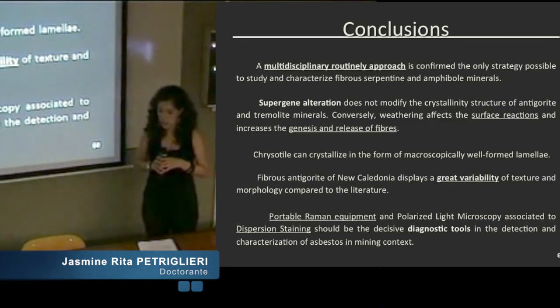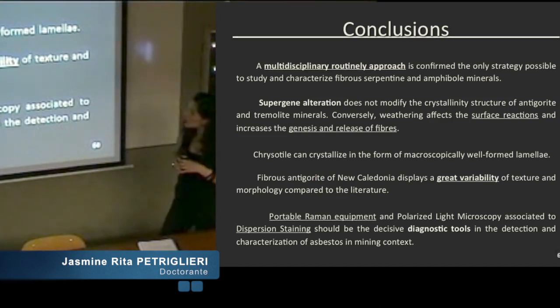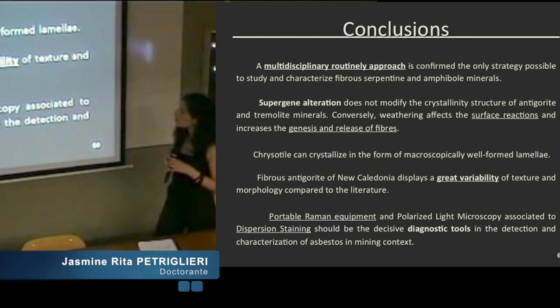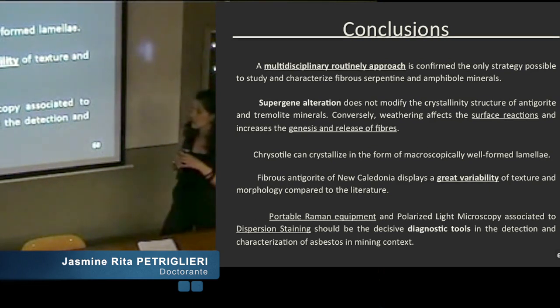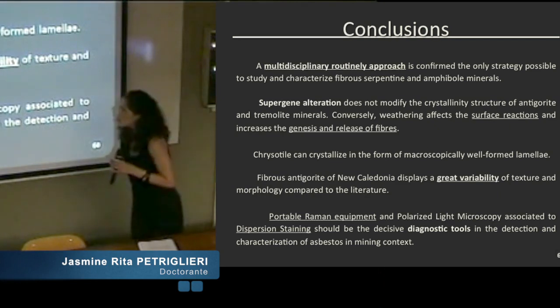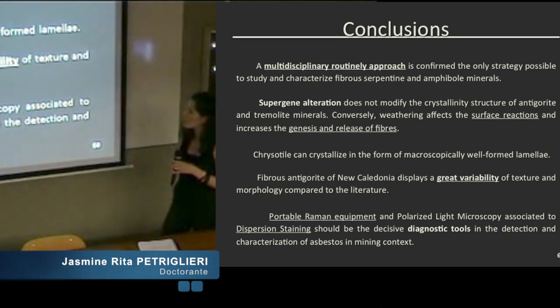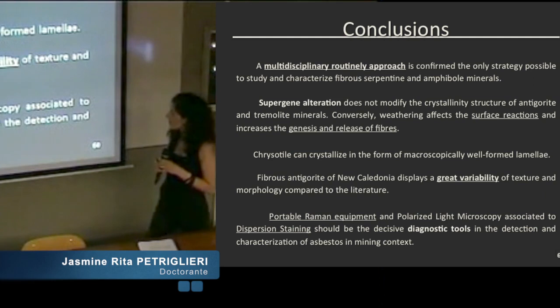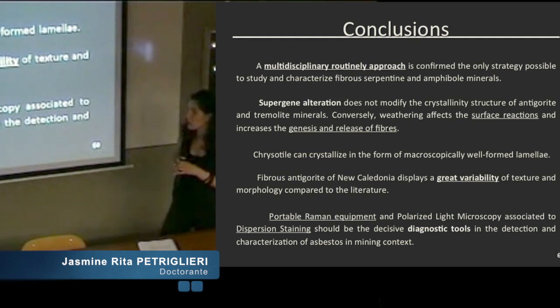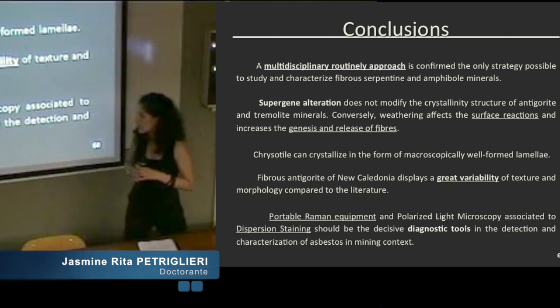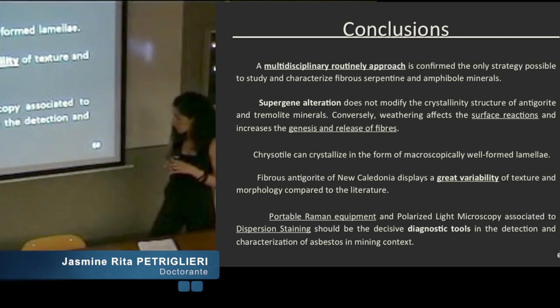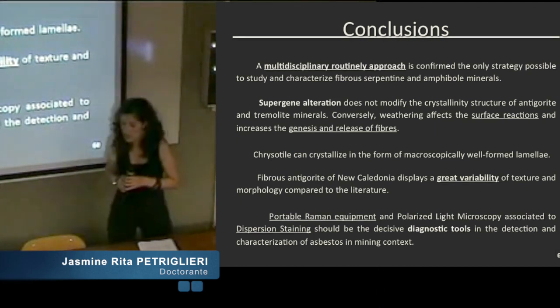To conclude, a multidisciplinary routinely approach is confirmed as the only strategy possible to study and characterize fibrous serpentine and amphibole minerals. Supergene alteration does not modify the crystallinity of antigorite and tremolite but affects surface reactions and increases the genesis and release of fibers. It is important to remember that chrysotile can crystallize in the form of macroscopic well-formed lamellae, and fibrous antigorite of New Caledonia displays a great variability of texture and morphology compared to literature. Finally, the portable Raman equipment associated with dispersion staining observation should be the primary diagnostic tool in the detection and characterization of asbestos in the mining context.